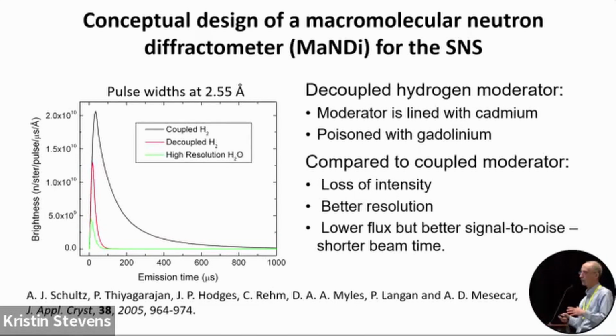So this is a moderator, so the liquid hydrogen in these moderators is about 1 liter. And if you line it with cadmium, except of course in the direction where the beam goes to the sample, then you decouple it from the beryllium scatterer that's surrounding the moderator to scatter neutrons back into the moderator. And it's also poisoned with gadolinium, with the gadolinium foil. And what this does is reduce the amount of time that neutrons can bounce around in the moderator. And so you get very good time resolution.